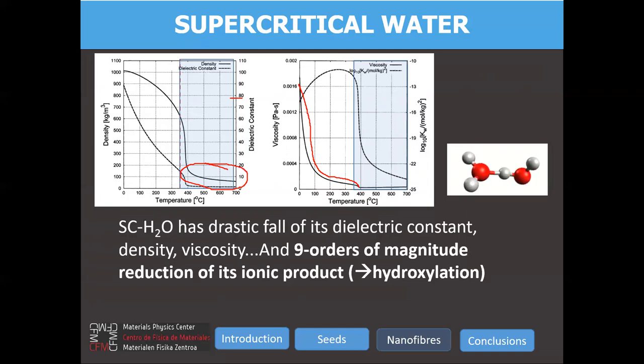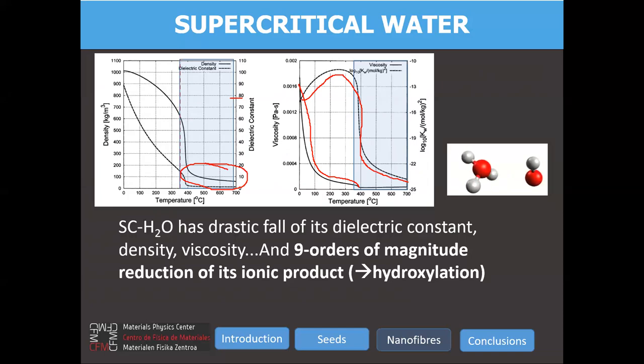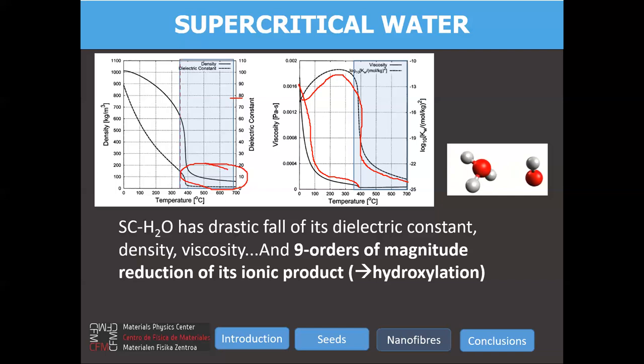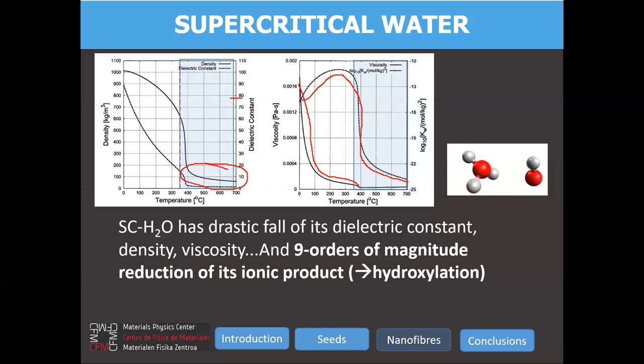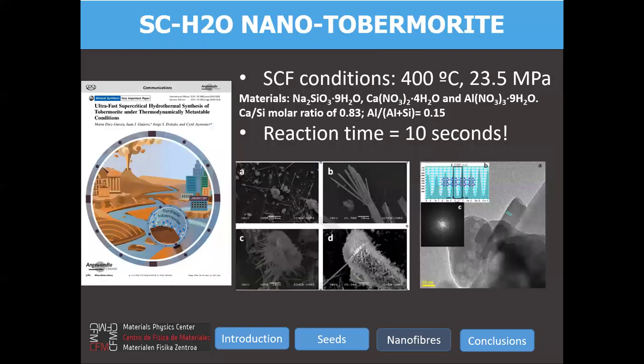What is most important for our talk is the ionic product of water. Just by entering the supercritical state, the ionic product decreases dramatically — you can get values below 10⁻²². This means a huge reduction in the amount of OH⁻ and H⁺ ions in the medium. In theory, the amount of OH available in supercritical water is very low, meaning the hydroxylation process is probably avoided. We therefore thought this was a good methodology to incorporate both effects: aluminum for raising the bond-breaking barrier, and supercritical conditions to avoid the hydroxylation process.